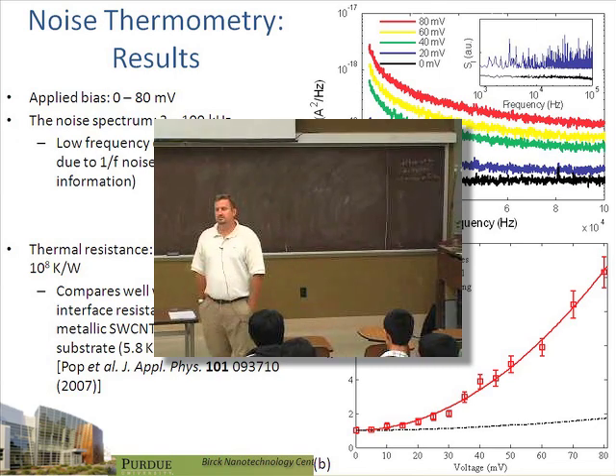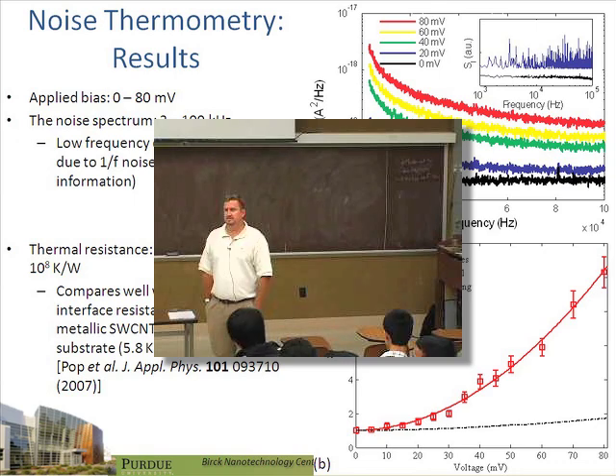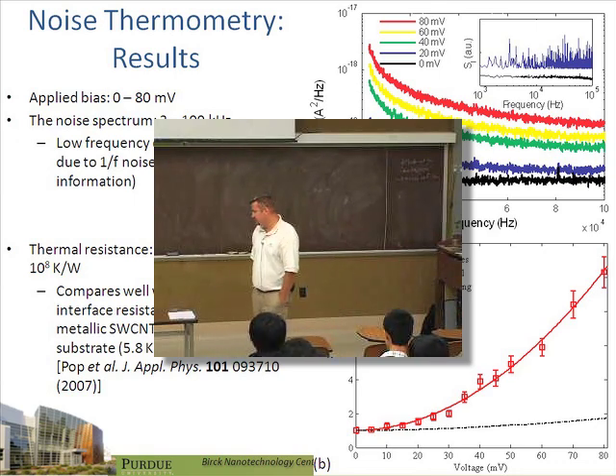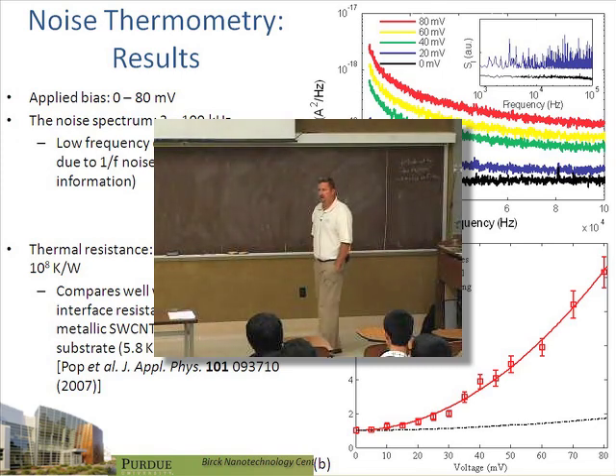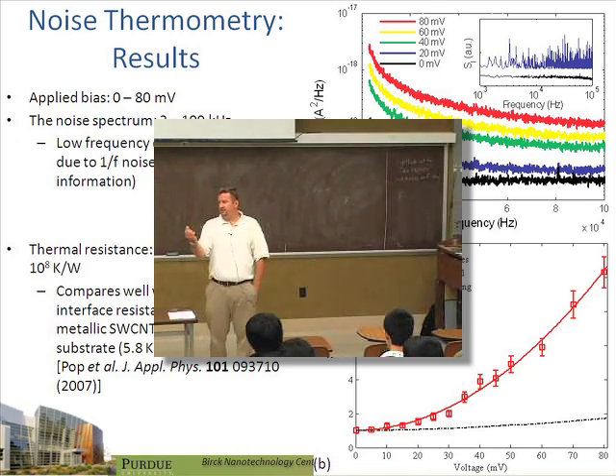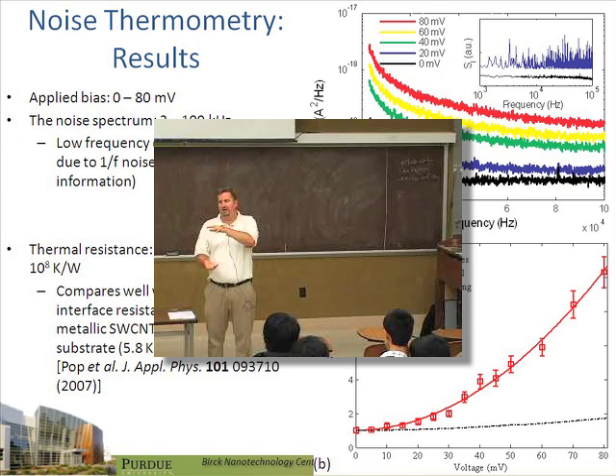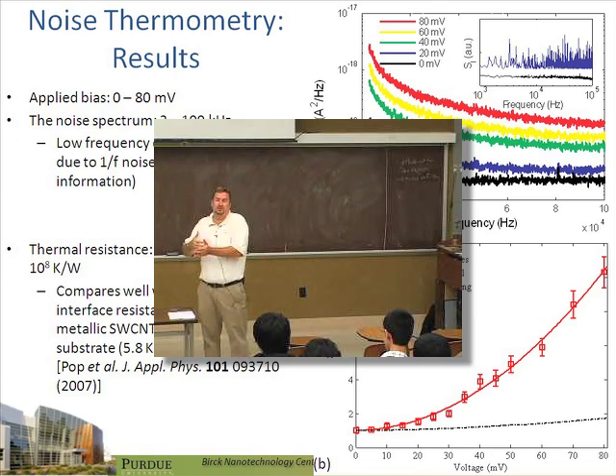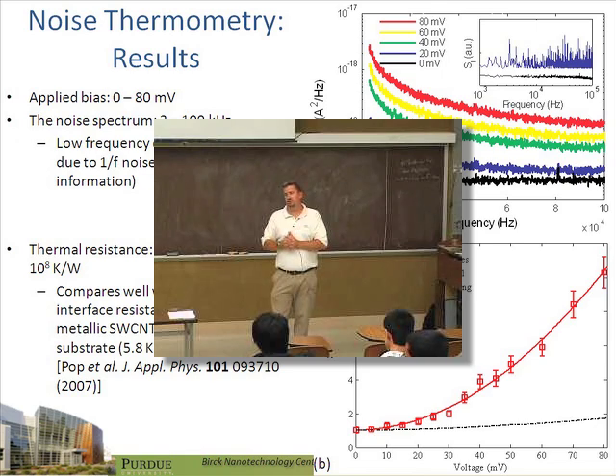Is there a crossover regime where electronic conductivity is higher than phonon conductivity? Conductivity due to phonons. Yeah, I would say if you took metal nanowires, and I haven't done this calculation, but my intuition tells me if I took metal nanowires down to a size at which you started to separate the bands, you would have too low an electron population around the Fermi level, which is what someone else so poignantly said is what counts for thermal transport. That would become so low that phonons would dominate. And then as you increase the cross-section of that wire and you increase the electron density of states around the Fermi level, you would certainly cross over to a place where the electronic contribution was bigger, if you started with a metal where the electronic contribution in the bulk is more than phonons, which most metals are.